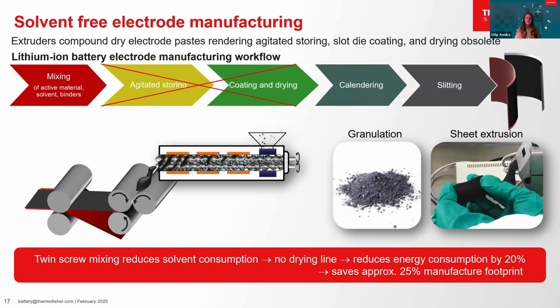The mixed material can be directly fed into a roller press and calendared onto the current collector foil without drying. This saves a lot of energy. Suitable binder formulations like PTFE or PVDF allow the dry cathode granulate mix to be calendared directly onto the current collector foil. PTFE forms fibrils under shear to bind the particles, but the shear must be controlled for proper fibrillation.